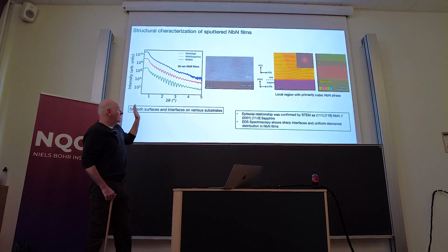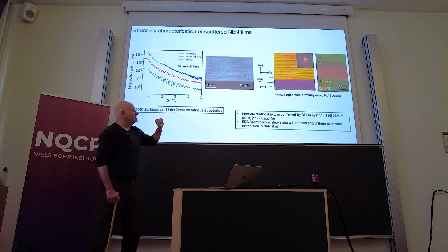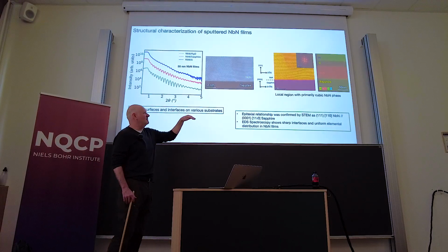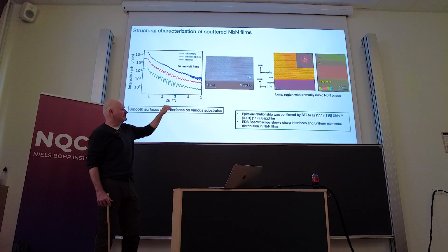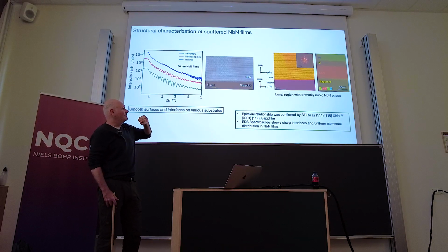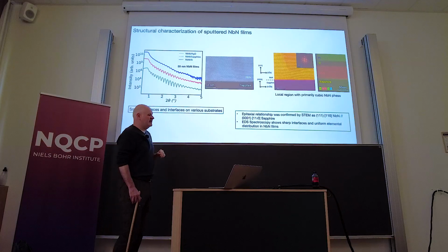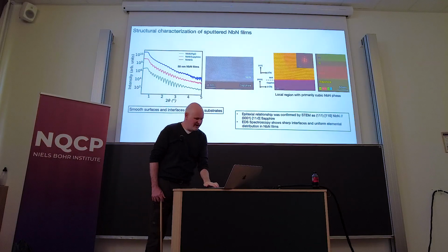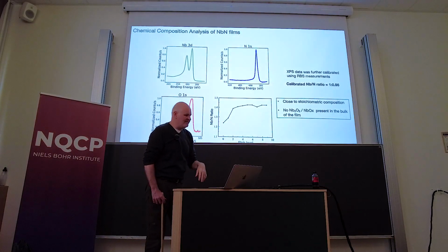We did X-ray reflectance and TEM cross sections, and you can get these beautiful epitaxial crystals grown off of sapphire with very little included oxygen.